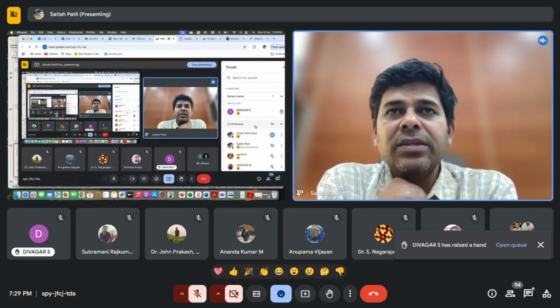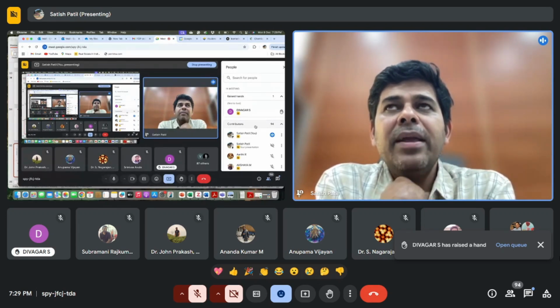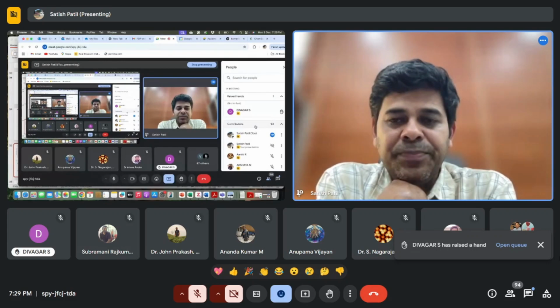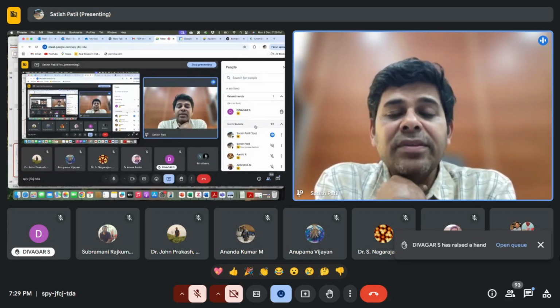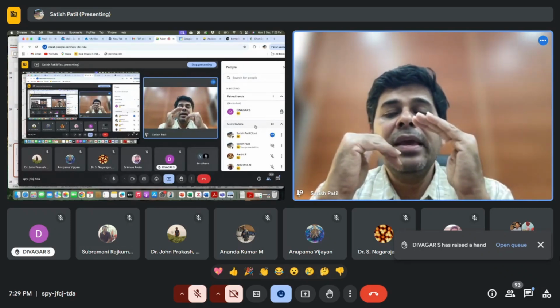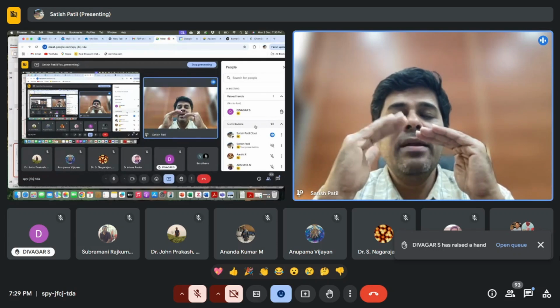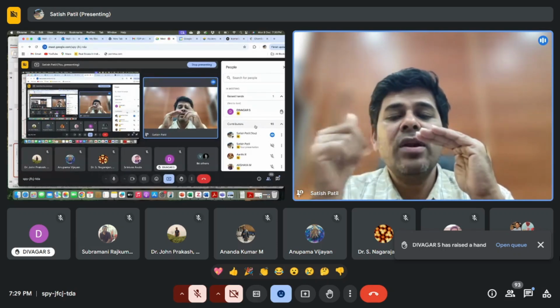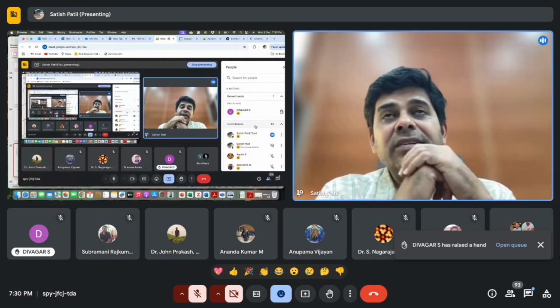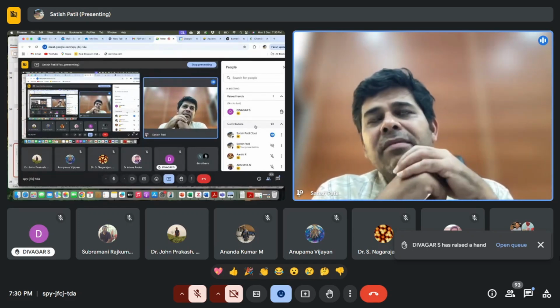Here you have HOMO-LUMO actually. The band bending you've seen in a conventional semiconductor, here there are no bands in principle. You have just discrete energy levels. So what defines the separation of a hole and electron is the difference in the energy gap. For example, LUMO of a p-type and LUMO of n-type. The delta E determines the electron transfer rate. That's called charge transfer. So here, due to discrete energy levels, band bending is not substantial as you see in silicon.